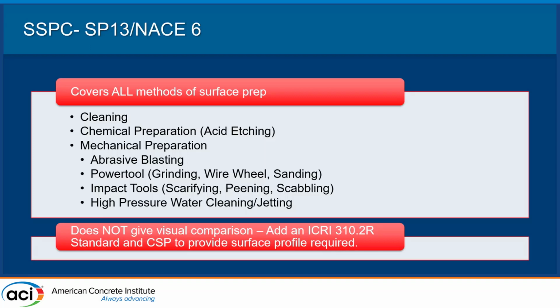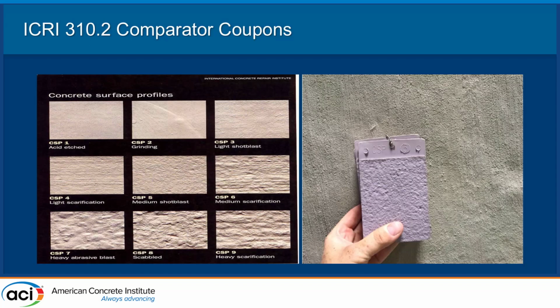It's very vague. So we recommend adding in the ICRI 310.2R standard concrete surface profile, and this provides a visual comparator. These here are rubber reproductions of different surface profiles. So you can specify an SSPC SP13 with an ICRI 310.2R concrete surface profile of 3 to 5. And then that gives you, this is a concrete surface profile 3, and this is a 5.